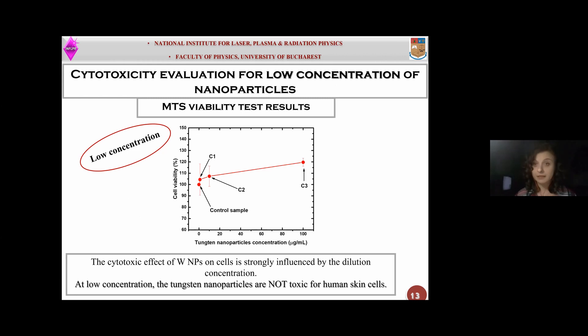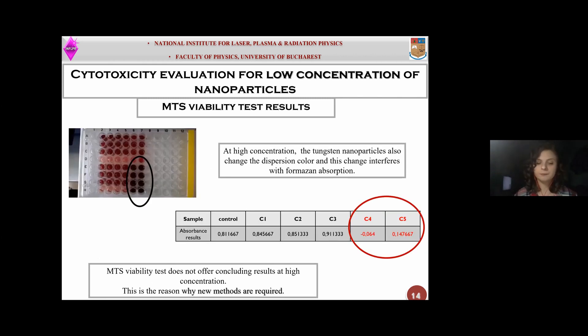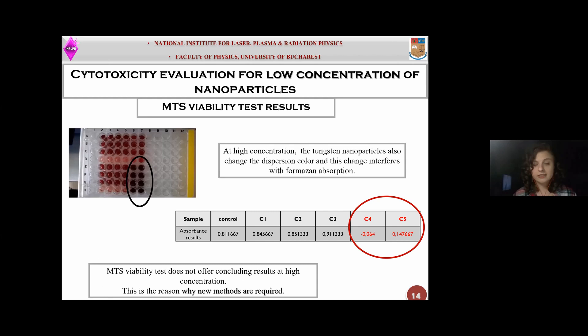This result is represented in the graphic, because no difference in viability is observed between the control sample and the low concentration samples. But when I added a higher concentration of nanoparticles over the cells, the nanoparticles' effect on the medium color interferes with optical measurements. So new methods for tungsten cytotoxicity evaluation are required.